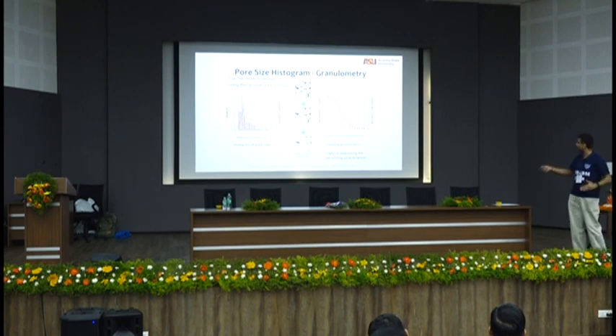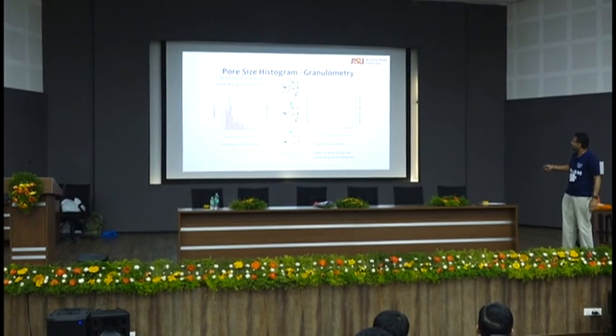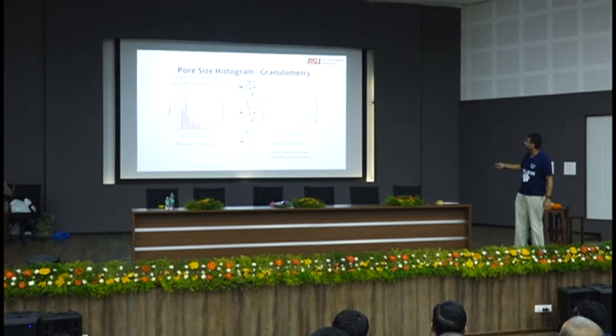So I can use a structuring element of a certain size and virtually close off pores sequentially in images. So if I use a structuring element of 2 mm, anything lower than 2 mm is ignored, right? And then I plot the radius of the structuring element as a function of what is remaining. Say, the radius here is 1 mm, the radius here is 2 mm, so I use a number of different points. I find out now the area fraction remaining. So at 0, I have all the area here, right? At 2, I have only this much area left. You see that? And then I get this red curve. All of you get the idea?